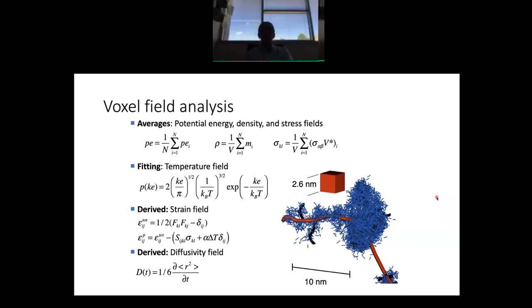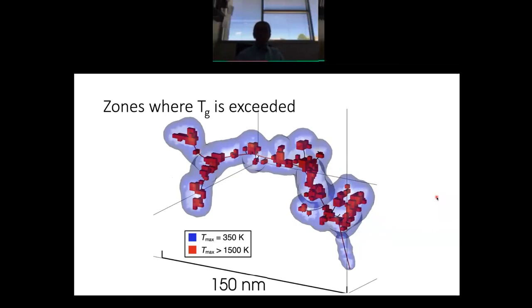So we carried out what's known as a voxel field analysis. We subdivided the model into voxels, a three-dimensional pixel, basically. In each one of those voxels, we were able to compute averages of potential energy, density and stress. We were able also to fit the temperature from the Maxwell-Boltzmann distribution. We were able to figure out the plastic strains and the diffusivities. A lot of detailed information coming from these simulations.